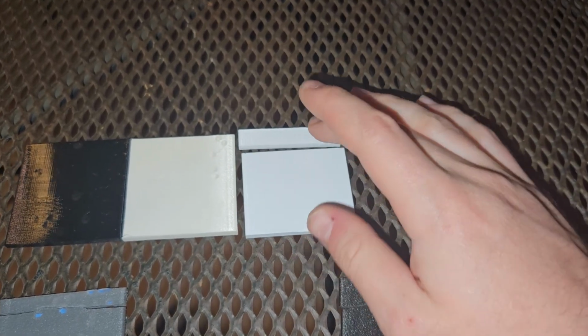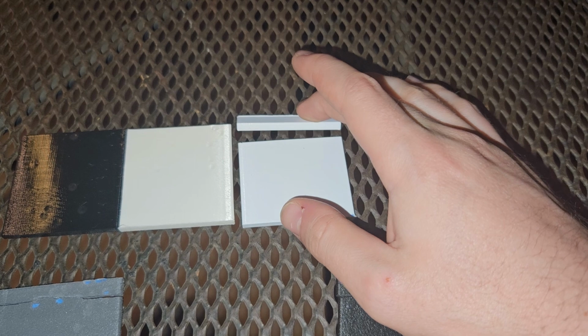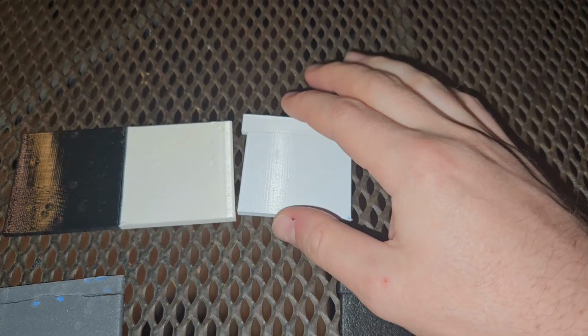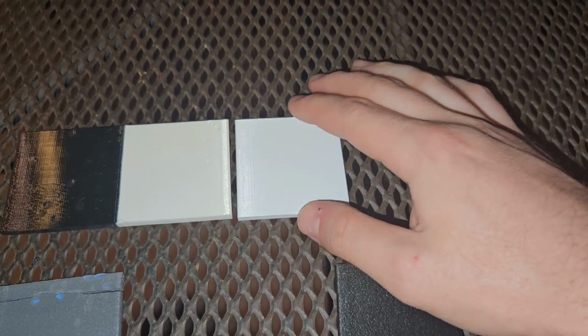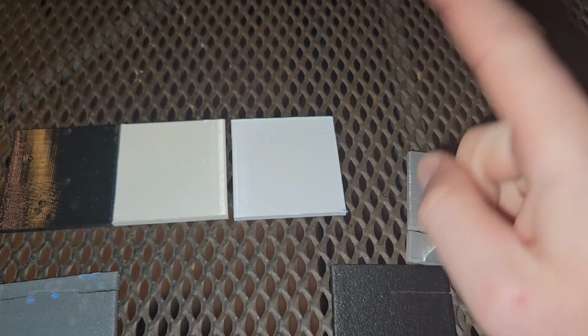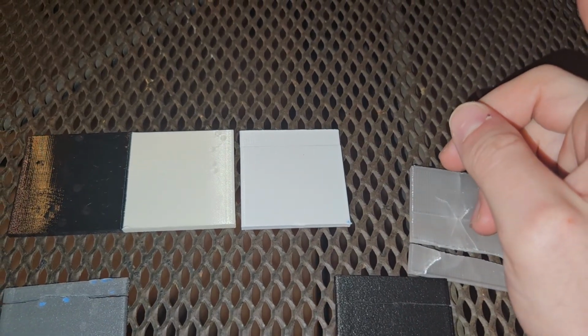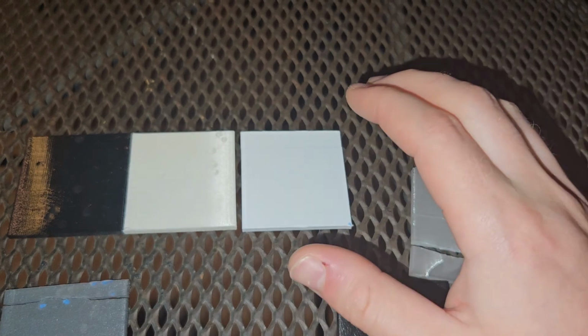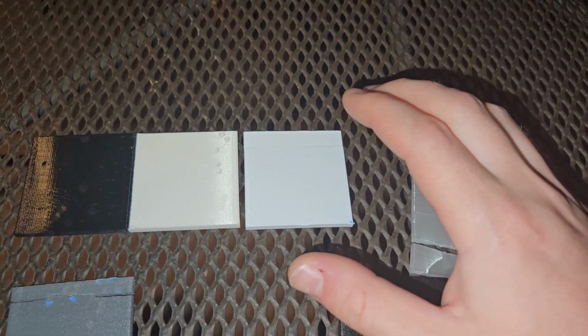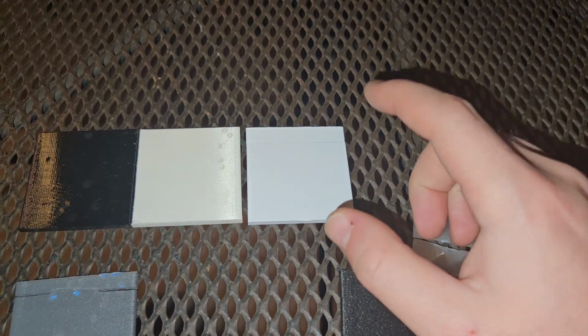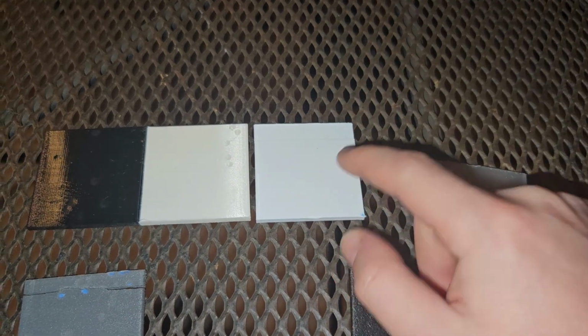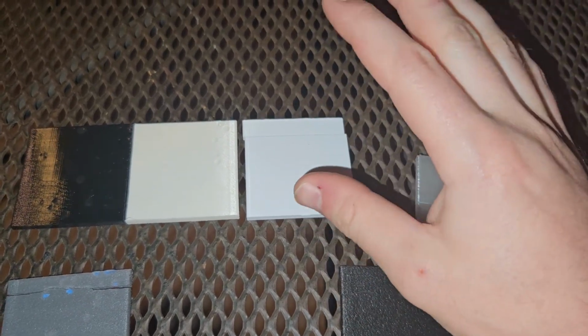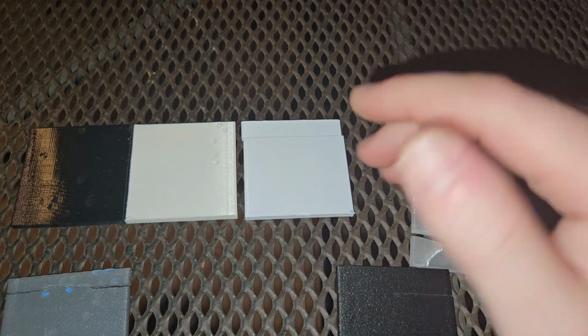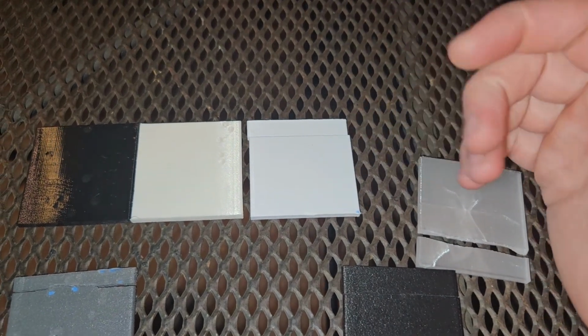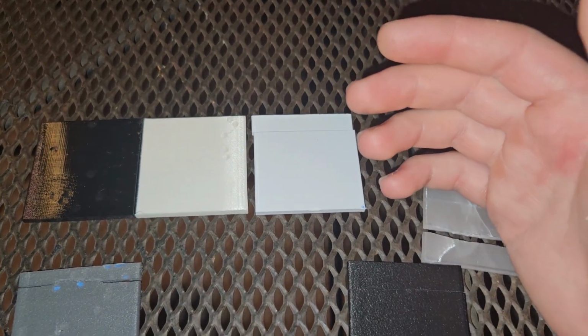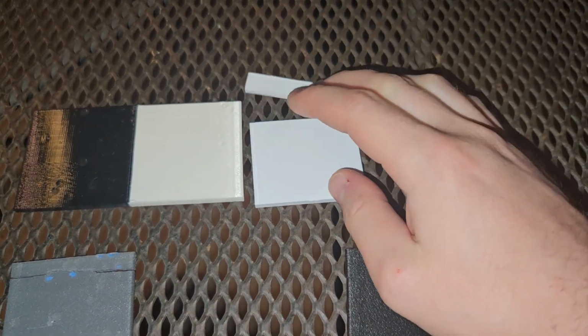I was very surprised to find that this cracked along this layer line. I did some testing earlier with one of these pieces not taped to the cinder block the way that these tests were, and I shot it probably 50 plus times and it didn't break. So I was very surprised to see this shatter on this layer line, but like I said, we have created a worst case scenario here. We're on the cinder block wall, we're shooting a hot gun, we're shooting from only about 10 feet away, we're pretty close, and clearly it didn't quite hold up.